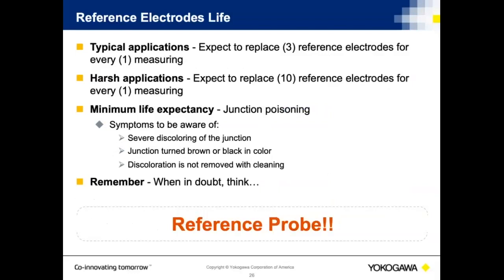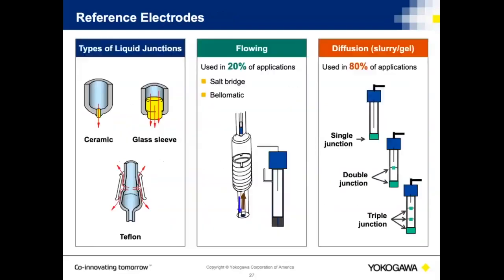Reference electrode life. You can expect to replace a reference electrode 3 times more than a measuring electrode. If you're in a harsh application, you could go through as many as 10 reference electrodes for every 1 measuring electrode. The issue is, depending on what the application is, will determine how long that reference electrode is going to last. Even after doing this many years, I get the selection of the reference electrode correct probably 60 to 70% of the time. Other times, I have to go through different iterations of reference electrodes.